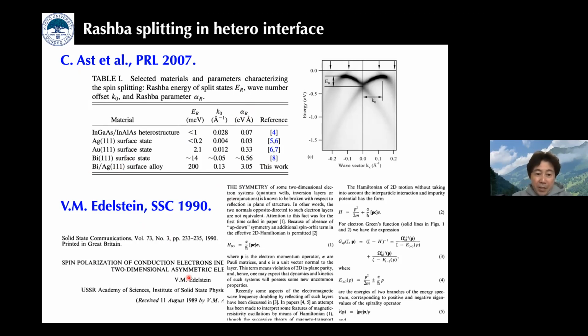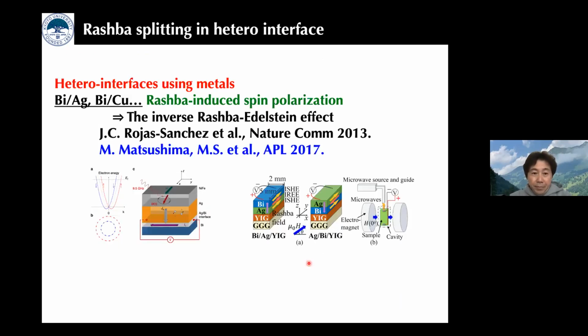And this is a very small, simple paper, but the contents of this paper are very, very fruitful. And he theoretically proposed the possibility of efficient spin conversion in this system. And in fact, a group in France, headed by Albert Fert, first reported the efficient spin conversion by using the bismuth silver system, because such Rashba splitting exists at the interface.